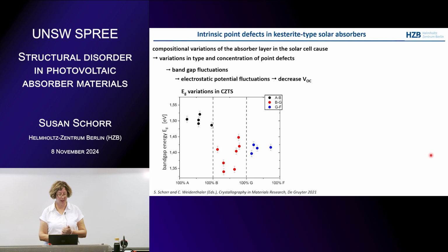You always have to keep in mind that in your thin film you will have compositional variations. And this is also something you should try to avoid, because if you have compositional variations, you have variations in the off-stoichiometry type, and with these variations in your point defect concentrations. And because of that, you will have bandgap fluctuations.